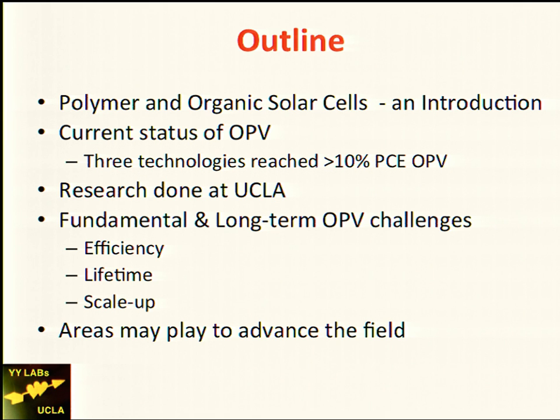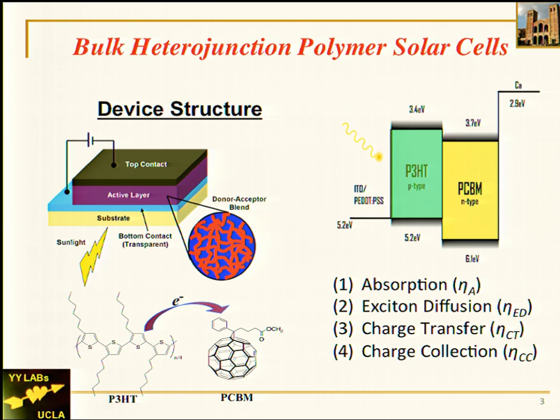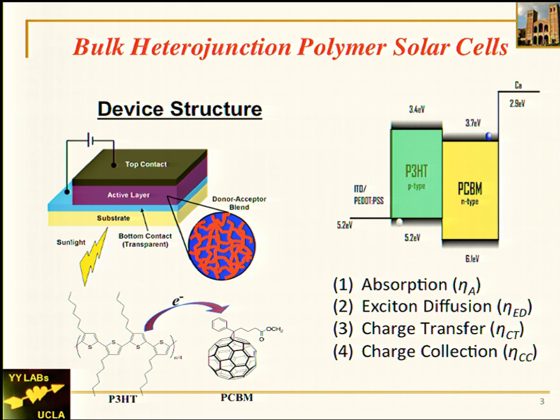Now let's change gear to organic photovoltaics, which is the reverse of organic LEDs — we produce electricity from photons. The key component is the so-called bulk heterojunction, which is a mixture of two materials. Photovoltaics is basically about junctions: how to create a junction and how to separate charges. When a photon from the Sun hits the heterojunction, it creates electron-hole pairs which then need to be separated.